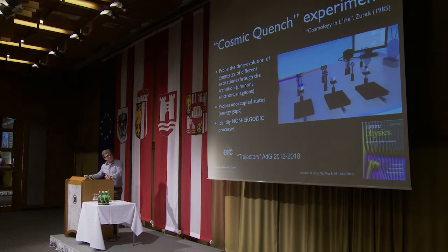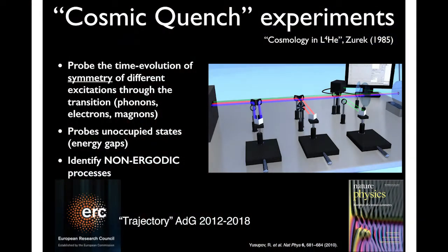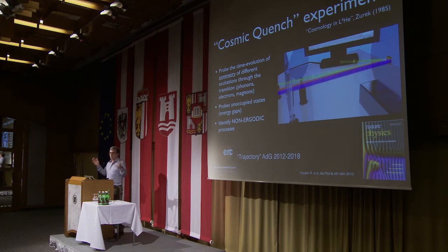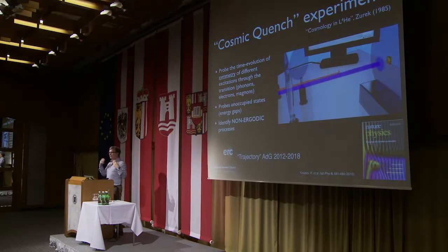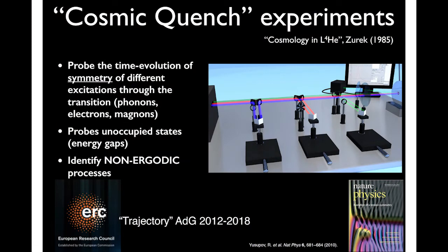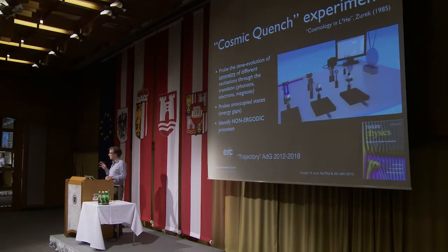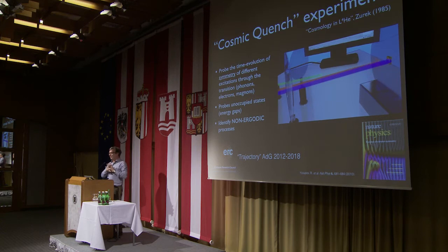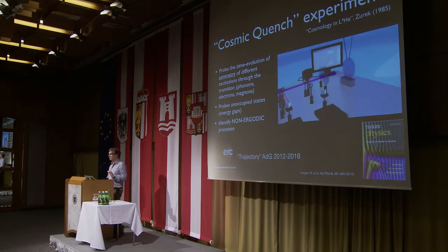Now, how do we do that? It's very straightforward, conceptually. Imagine any kind of system that you can somehow study optically. What you do is you have one short pulse which basically heats up your material or forces it into the non-ordered state. That's the first laser pulse. It's sort of blue, and it impinges on the crystal. The other two are doing pump-probe spectroscopy, femtosecond spectroscopy, which is designed to test how the system is evolving after you've disturbed it by the first pulse. Conceptually that's quite straightforward: time-resolved spectroscopy as the system is evolving in time. That's a rather new way of doing things, but it tells us rather new things.